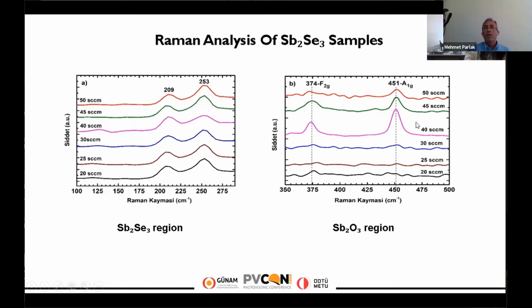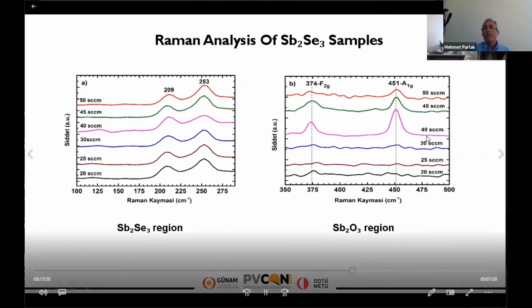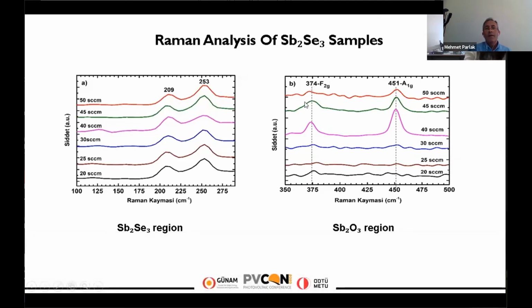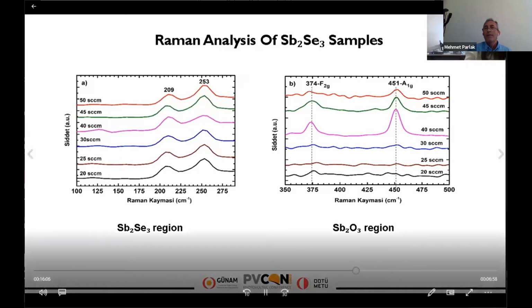In the films which I have grown using 40 SCCM argon and above, oxide phases were observed. Here you see peaks at 374 and 451.